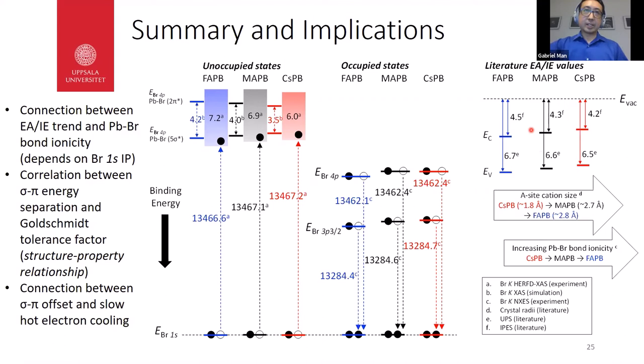The second thing we found is a correlation with the pi sigma energy offset. There's a correlation between this offset in the conduction band and the Goldschmidt tolerance factor. So this is a direct structural property relationship. We think that this offset has something to do with the differences in how hot electrons cool. If we assume that the pi states and the sigma states have different carrier scattering rates, then maybe we can put an argument together for how this would affect the mechanism of hot carrier cooling. But I won't go into that right now.